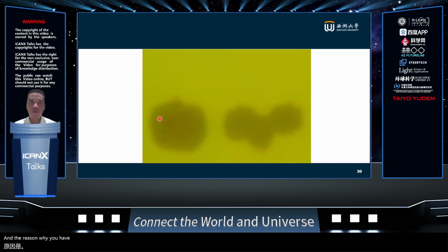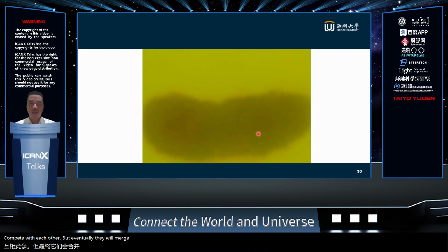The reason why you have several parts of this grating is that there might be several larger seeds or larger nanoparticles, and they all compete with each other, but eventually they will merge. The reason they merge to be quite similar is that as long as we control the polarization, which in this case is parallel like this, no matter how they grow, they will always grow along these lines. Let me show you again that they grow into very large, beautiful, almost precisely controlled gratings.